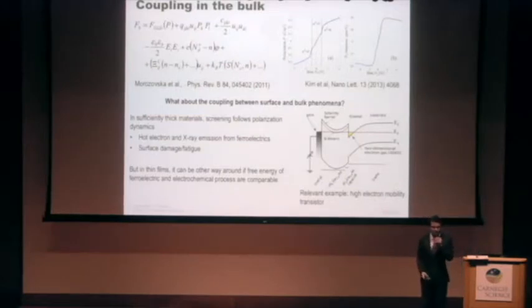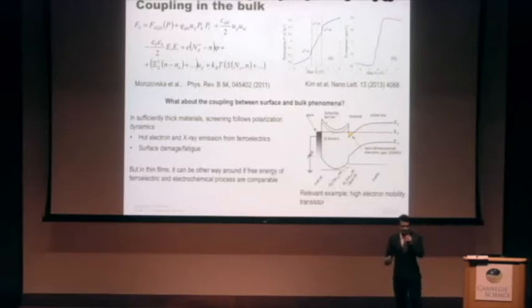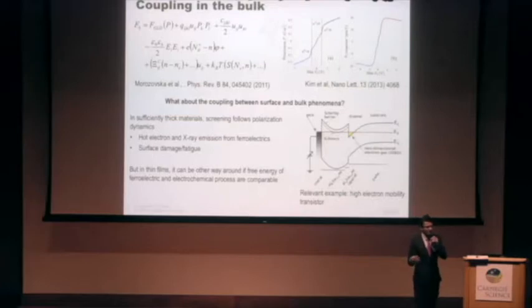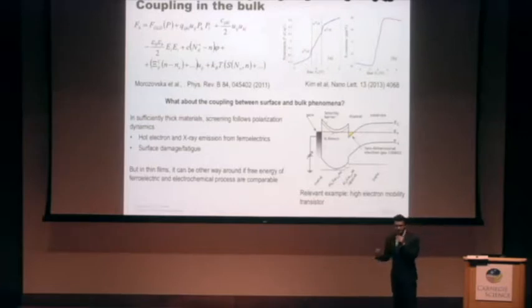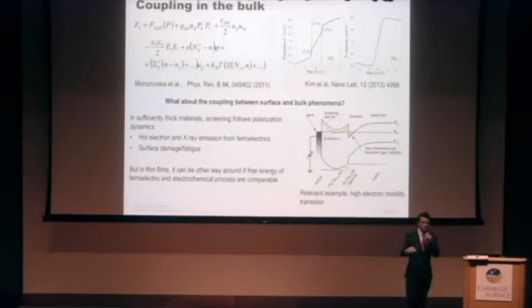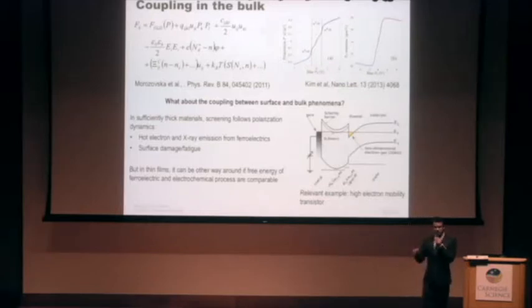If you look at bulk ferroelectrics, you can pretty much write Landau expansions, and you can predict properties pretty well with current Landau theory. You can go ahead and add these terms. In general, you don't have to worry about the surface so much because, as I said before, the bulk polarization energy is so much higher that the surface really has to follow whatever the bulk does. So it's not so important when you're looking at single crystals. But we're in the thin film session, and when you go to 30 nanometers or thinner, what we find is that the surface electrochemical processes become on the order of the same energy scales as the bulk polarization energy, and so you have some very nice mixed states that form, which I'll get into in the next few slides.